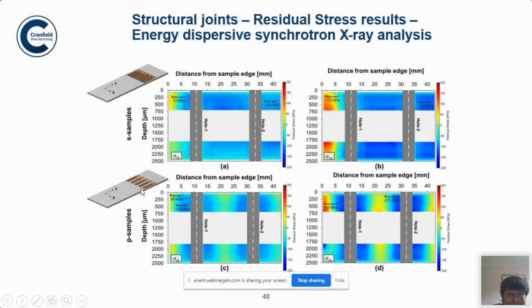Whereas with the patch, you create the compressive stresses around the holes, but in between two patches the balancing stress field is forming. So this particular design is more useful because a crack will never start from here. The crack will start somewhere from here, and you are creating a large compressive stress around that, but the crack will propagate through the thickness, and therefore you are minimizing the tensile here because your balancing tensile is forming here. These are the things that you need to understand when you design a component for a particular application.